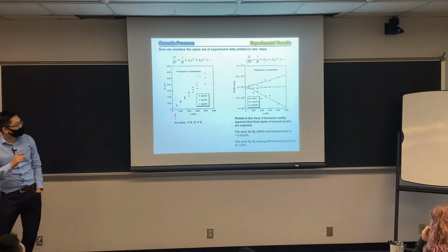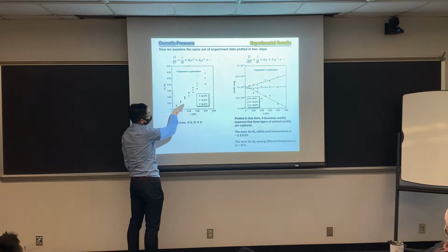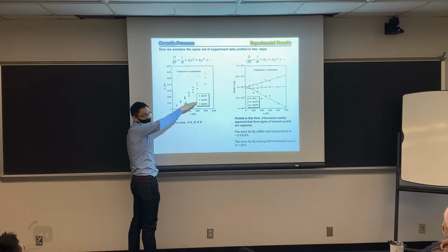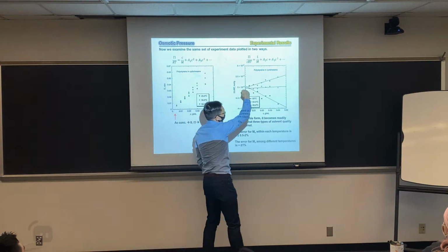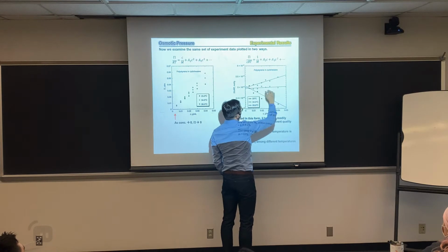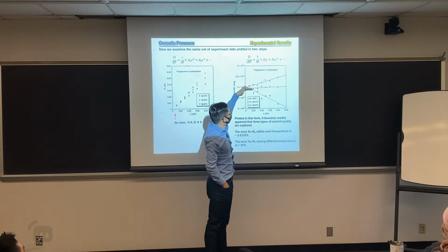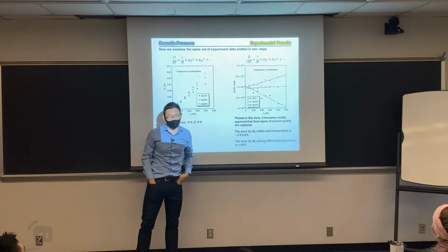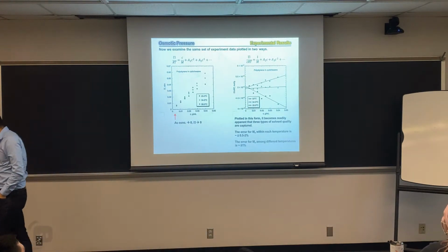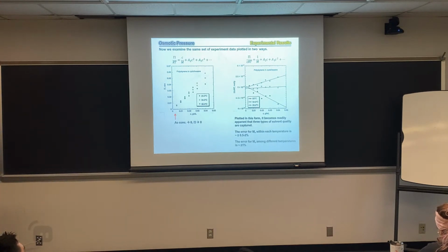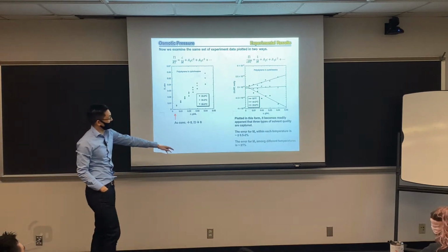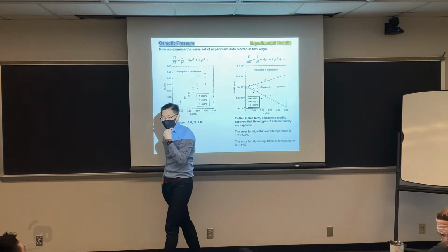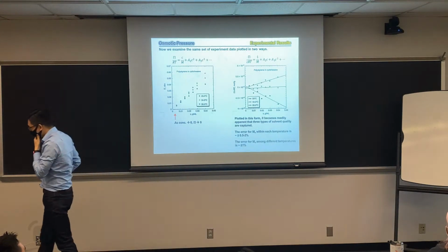You just need to measure, like we show here. I'm going to jump to it again. Put a polymer in a solvent, measure osmotic pressure, and modulate temperature. It will change the interaction between polymer and solvent. Then go back and look at the slope. When A2 is 0, that will be the theta condition, for polystyrene in cyclohexane roughly 34.5 degrees. At low temperature, it's a bad solvent. At high temperature, it's apparently a good solvent, as the slope is larger than 0. Correct?